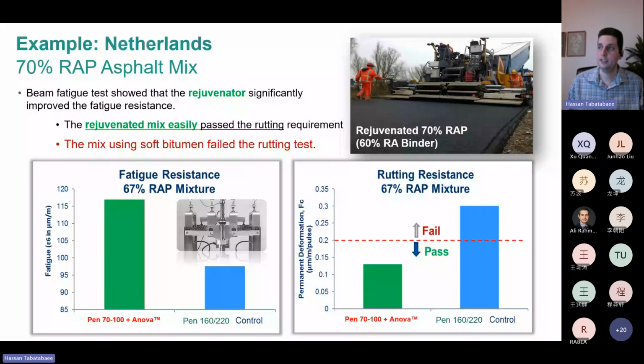Netherlands have been using recycling agents and rejuvenators for 70 to 85% RAP for years now, and they have performance testing using their beam fatigue testing and a dynamic rutting test. And you can see here that actually using a paving grade asphalt with the rejuvenator, you have a better ability to balance cracking resistance against rutting than you do if you use a very soft bitumen like a Pen 160-220 for the same mixes, where you are unable to meet cracking without failing the rutting performance. This is very normal performance. I would say at this point, maybe 70% of the asphalt plants in Netherlands are using this type of technology. So it is very common to use this very high RAP content with rejuvenation.